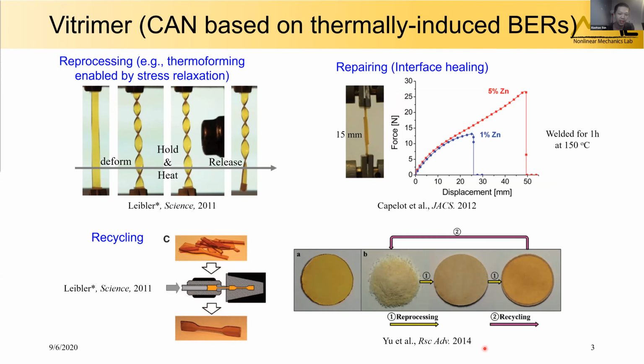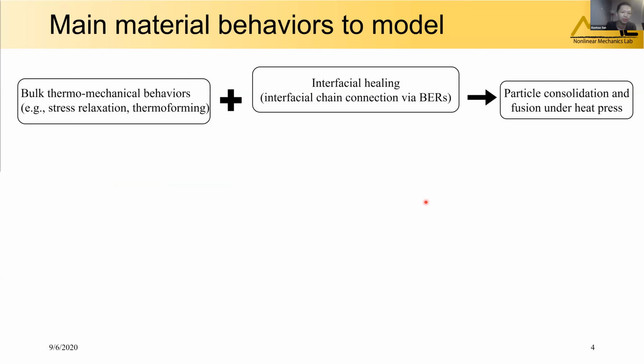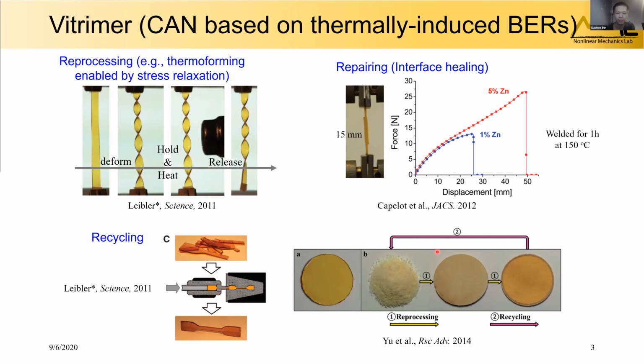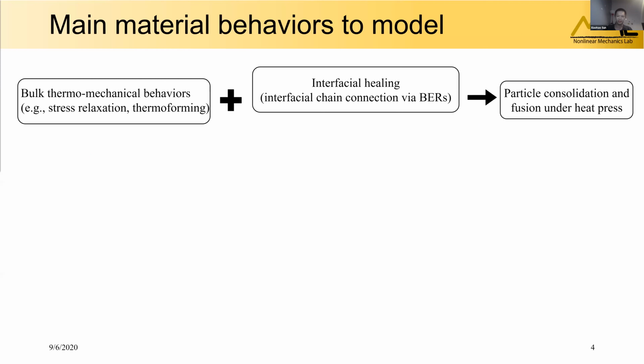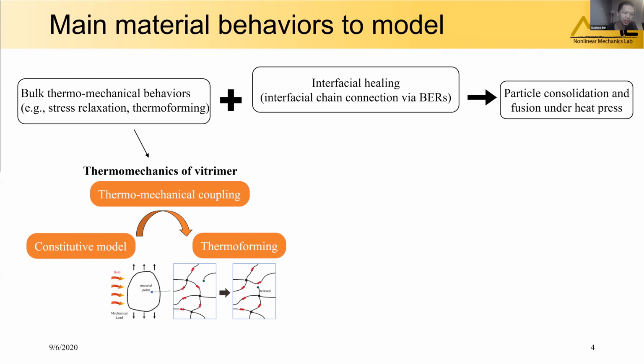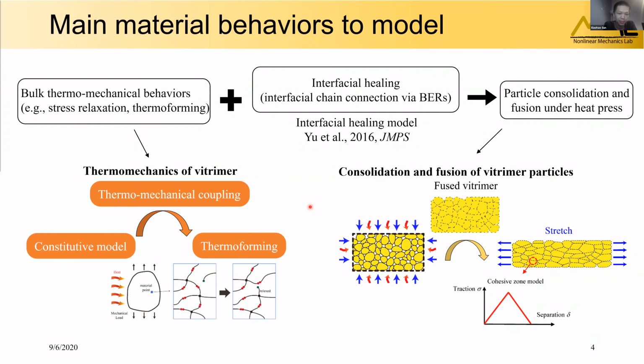We, in 2014, have also demonstrated the Vitrimer can be recycled from the powder through a heat press process. So in the above applications, there are two fundamental behaviors, the bulk stress relaxation behavior and the interfacial healing behavior. The two behaviors enable the capability of particle consolidation and fusion under the heat press, which is a fundamental process underlying this powder-based recycling. So our work is to understand and model these material behaviors. We will first focus on the bulk material behavior, the thermomechanics of the Vitrimer, and then using the interfacial healing model developed by Yu, we will study the consolidation and fusion of the Vitrimer particles under the heat press.